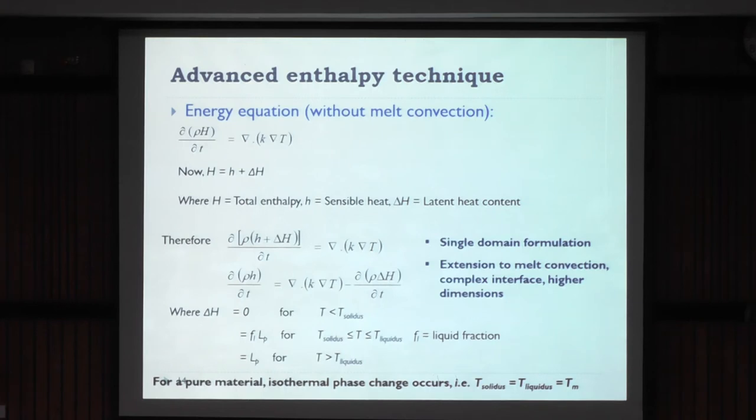So momentum I haven't shown here. Now this term is zero during solid, and during liquid this will be rho into L, meaning full latent heat will be there. However, during phase change this term will have some value ranging from zero to the full latent heat value.